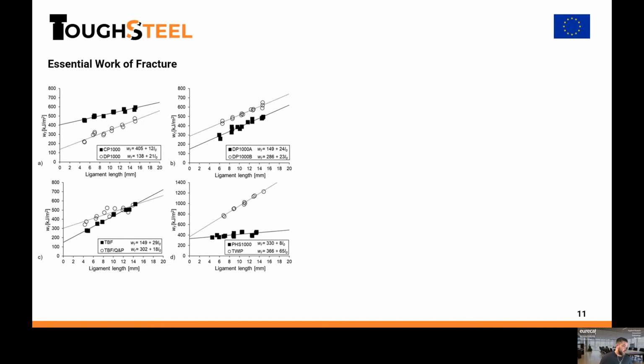Here are some examples of application of the essential work of fracture methodology to different advanced high strength steels, similar to those shown before with the J integral. We have CPs, DP1000, several DPs, TRIP-assisted steels, third generation TRIP-assisted steels, press-hardened steels, and TWIPs. Here we can see, remember, the specific work of fracture, which scales with the ligament length, and then by linear regression or by extrapolation to zero ligament length, we can obtain the essential work of fracture, while the slope of this linear regression indicates the plastic work. As we can see, this is a very useful tool to define the different fracture behavior of the different materials. So we have validated this.